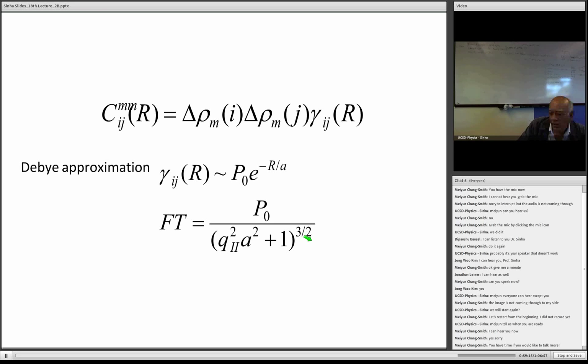And then, of course, if it's in a multilayer and the domains are correlated above each other, this domain scattering will be in streaks through the magnetic Bragg peaks. So I've tried to outline for you the broad features of diffuse scattering from roughness, magnetic scattering, diffuse scattering from magnetic domains, and how they fit together in multilayers. I haven't been able to go into the details very much, but they're in these notes, and if you read the papers and references given with these lecture notes, you can get more information.